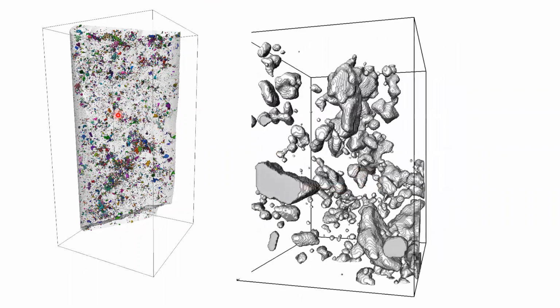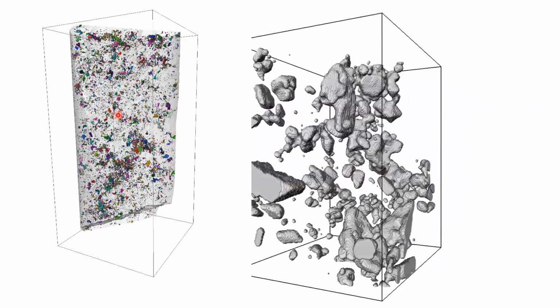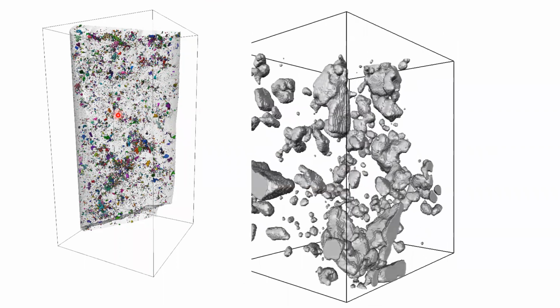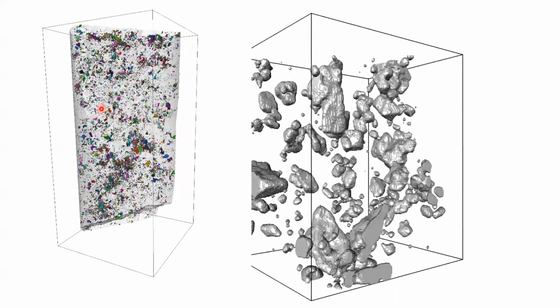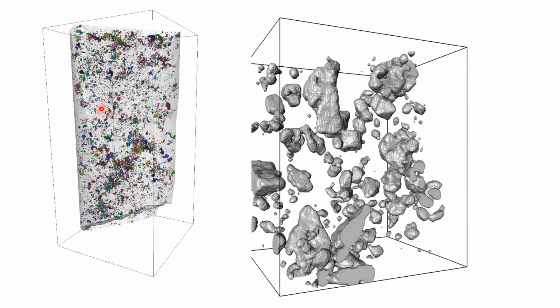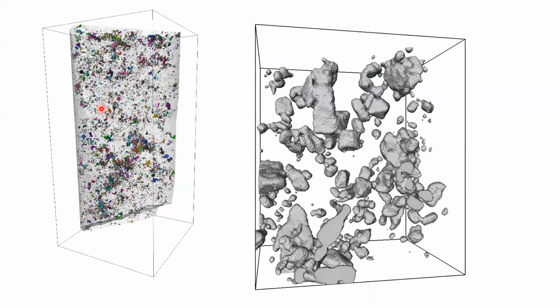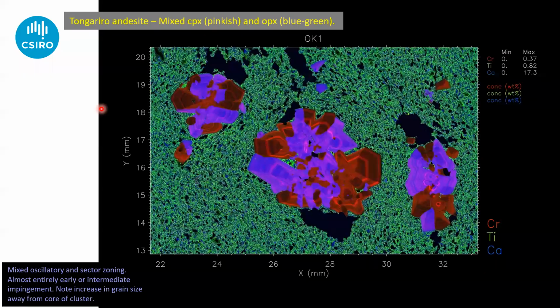And most of those crystals don't nucleate directly off that grain. They're nucleating independently. It's homogeneous nucleation, but homogeneous nucleation in clouds around pre-existing seed crystals. And we think that's the phenomenon of secondary nucleation, which I spoke about yesterday. So I just wanted to show you this one. This is nothing to do with chromite, but it's such a cool image that I wanted to show it to you anyway.